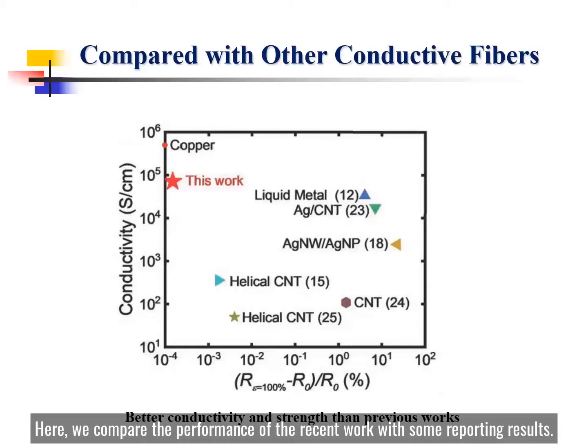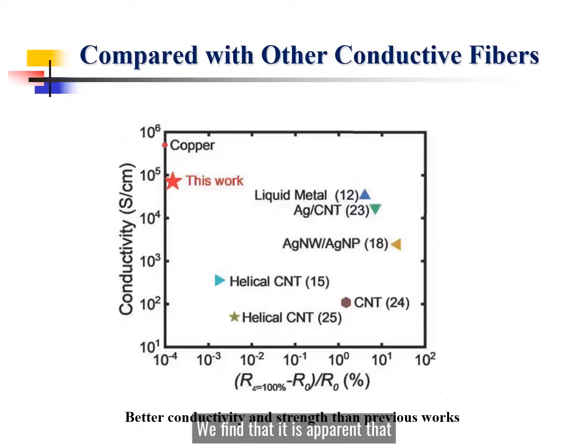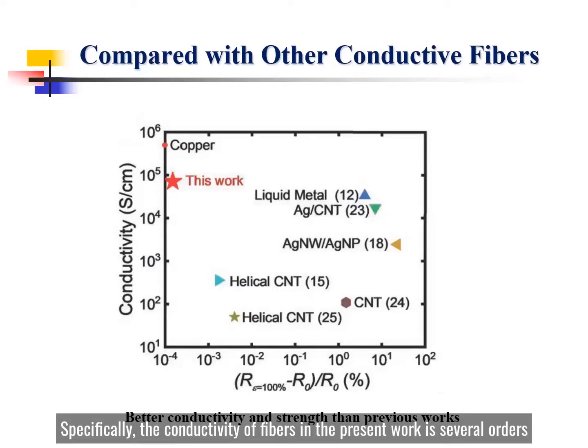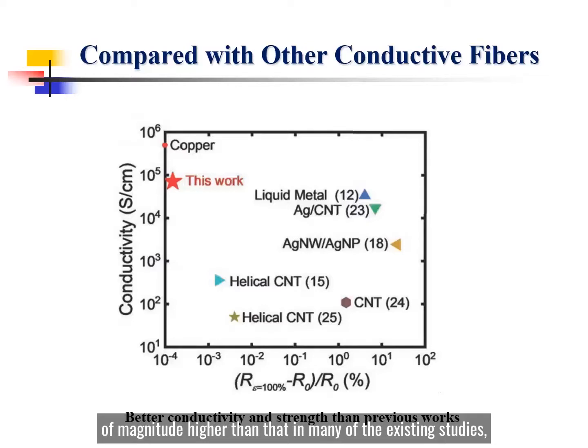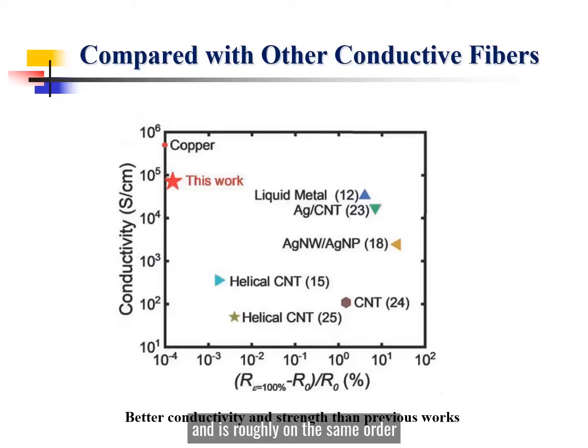Here we compare the performance of the present work with some reported results. We find that it is apparent that the present work outperforms all the reported results in terms of both the conductivity and the relative variation in electrical resistance. Specifically, the conductivity of fibers in the present work is several orders of magnitude higher than that in many of the existing studies, and is roughly on the same order of magnitude as the conductivity of the commercial carbon fibers.